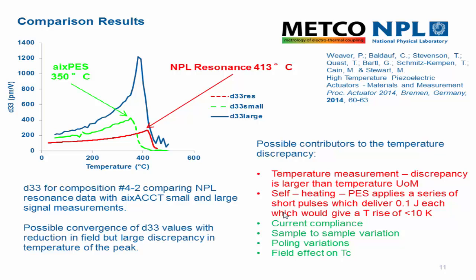Some of the other things that have an influence on this, things like sample-to-sample variation. I think Tim has shown some results showing the variation in the room temperature values. Certainly they're all quite consistent, but there could be variations in poling from sample to sample on these. These samples have to be repoled, and depending on how exactly that repoling procedure is carried out, we may get some variations.